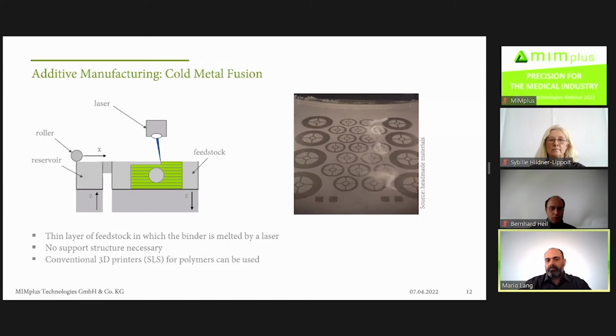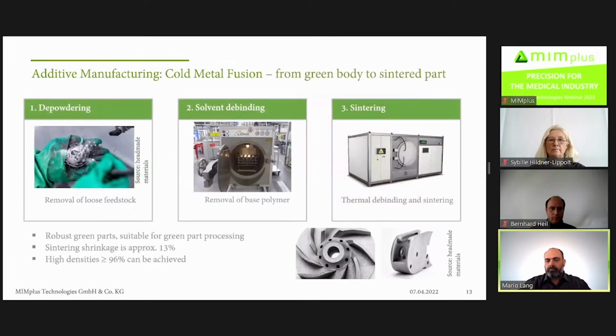The opportunity of this is you don't need support structures, because you have the bed of the powder surrounding your part and giving the stability to this. And you can use the cheap conventional 3D printers. After that, of course, you have to remove the loose feedstock, the rest of the powder, then do the debinding and the sintering to get your metal part.